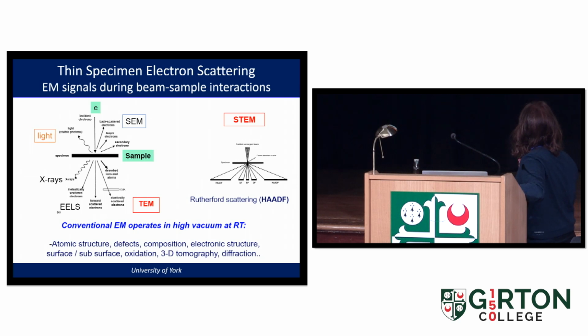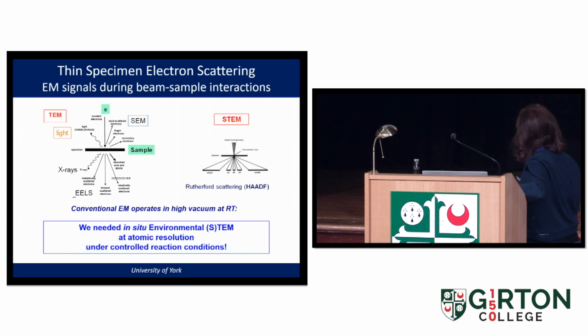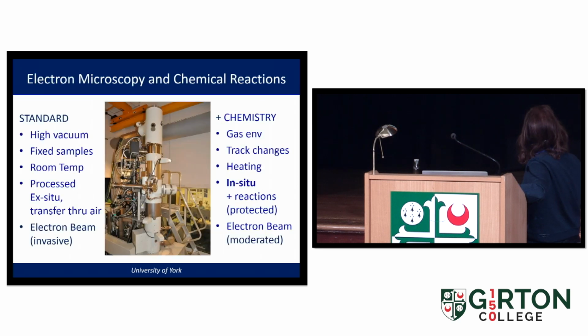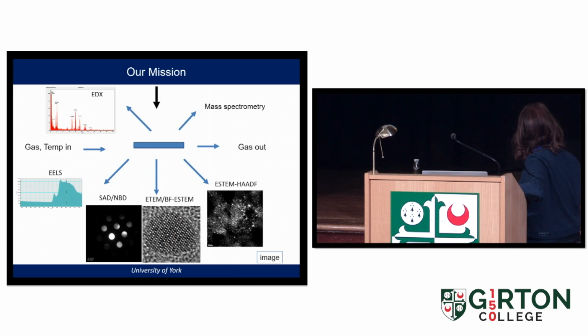Many researchers have used this conventional microscopy to do atomic structure imaging, composition, and structural modifications called defects, etc. Very nice work, but unfortunately, we need these under reaction conditions. So that's the challenge. So basically, this is our electron microscope. In a standard configuration, it has high vacuum and room temperature, but we want to have chemical reactions under gas environments, under in situ conditions, under heating, etc. So that's what we need to do. In other words, we need to incorporate all these signals, imaging, diffraction, chemical composition, gas, temperatures, mass spectrometry to analyze the reactants and the products, everything in one microscope. So that was the challenge.